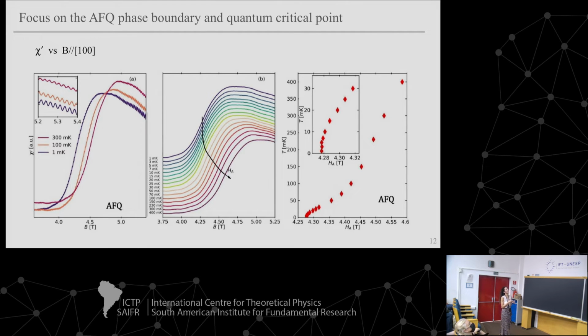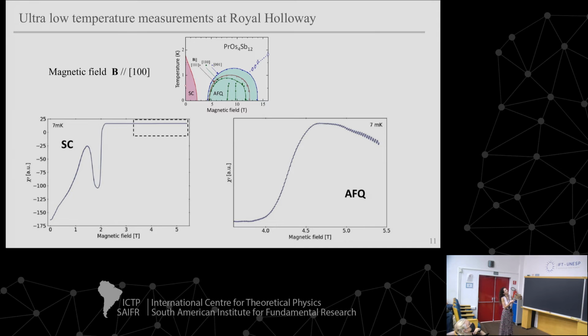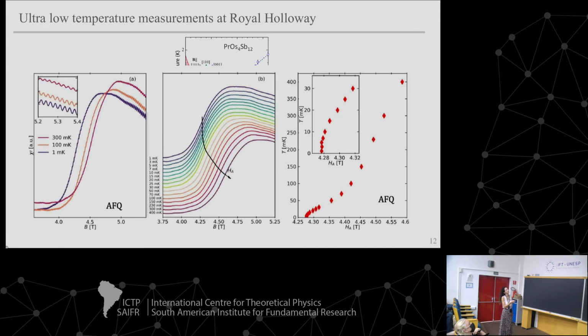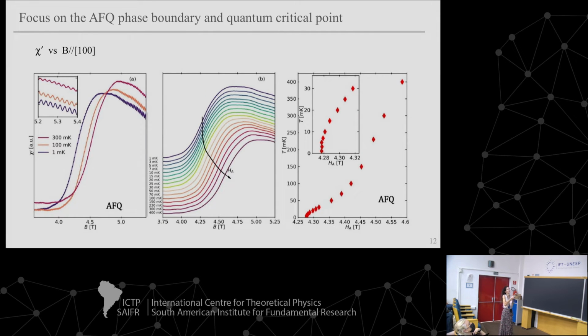All right, so what we did is we measured across this transition. We wanted to see what happened to the phase boundary. We've got the magnetic field parallel to the [100] axis, or direction, of the crystal. We did this at multiple temperatures, so this is 300 millikelvin, 100 millikelvin, 1 millikelvin, just to illustrate how the phase boundary is shifting with temperature, even down to the lower temperatures. Again, the quantum oscillations are very nice there on top.